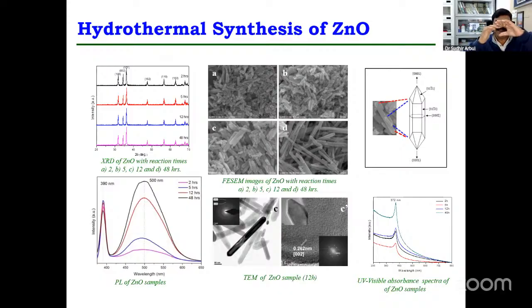Okay. And there may be some zinc vacancies or oxygen vacancies. That is a debatable issue. The 500 nanometer peak is due to zinc vacancies or oxygen vacancies, that is not confirmed. But there is some particular vacancy or defect. At that point, this electron gets transferred, and due to this transfer, we are getting a peak at 500 nanometer.